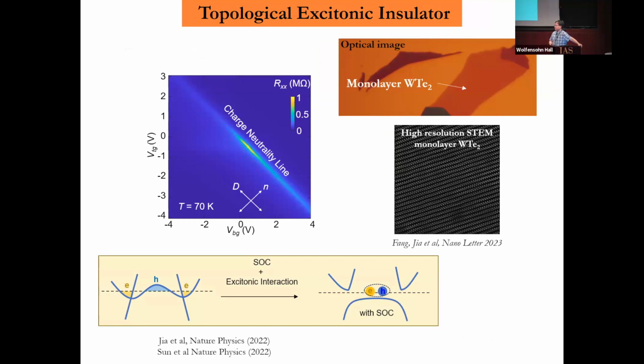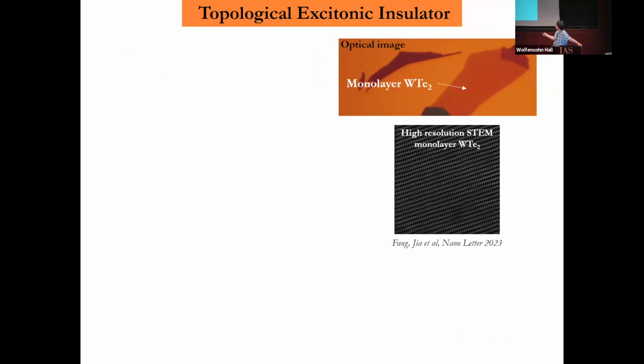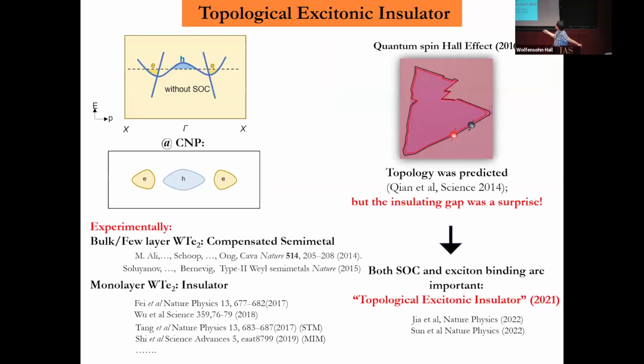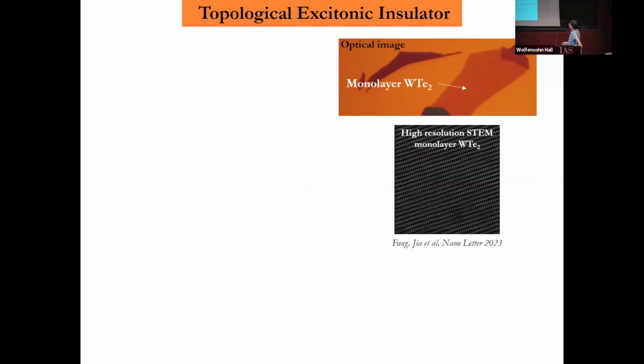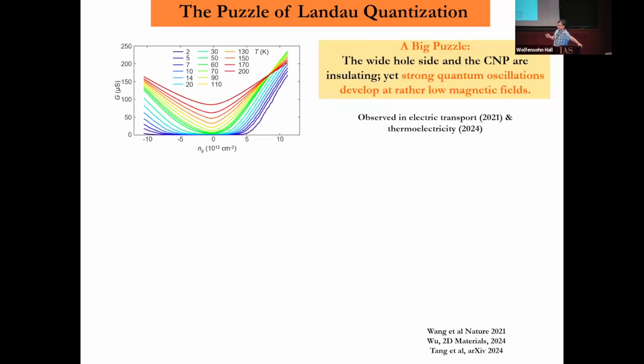We don't get this cone at the high symmetry point, because generally we have all the maxima and minima of valence band and conduction band at the high symmetry points. But is there any particular reason why these are not at the high symmetry points? This cone is not at the high symmetry point, and I don't think it's a symmetry reason you'd expect it there in this case. It's a semi-metal actually, it doesn't really have a gap, so you have a special point there. The band structure doesn't violate anything if it happens here. What's really amazing in this material is...